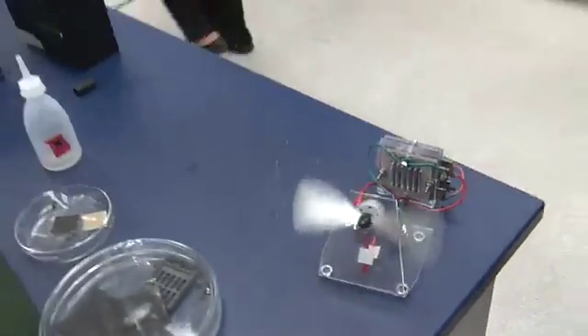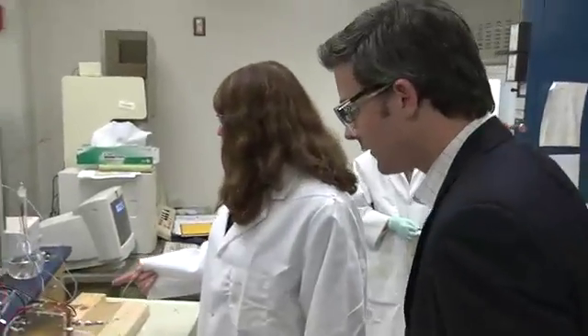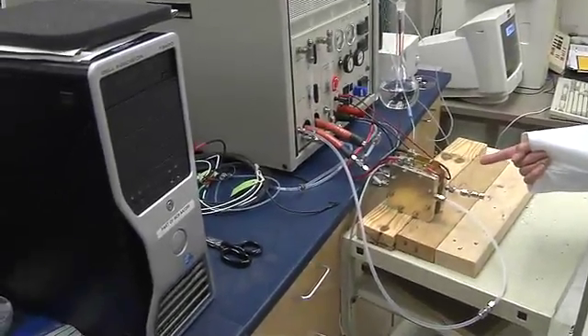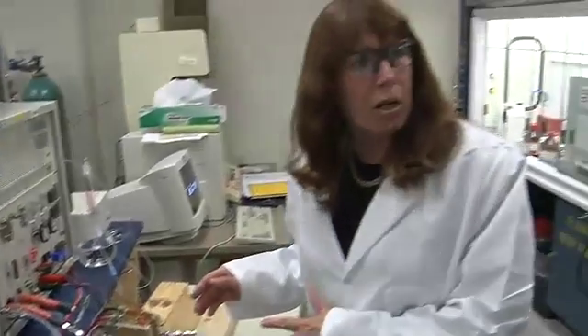This fuel cell currently being tested is an alkaline fuel cell — more of a 20-watt system. This is one of the experimental membranes we're looking at: an alkaline membrane, meaning it's a hydroxide base-conducting membrane, as opposed to an acid membrane, which is what most fuel cells use. Our new program is alkaline, and we're evaluating these experimental membranes, seeing what the problems are and trying to make them better.